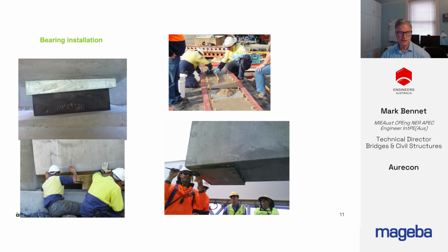There's been a range of different bearing installation details used over the years. A tapered machine plate is an acceptable attachment plate for an elastomeric bearing, but in New South Wales the common practice is to use a pre-moulded epoxy mortar pad bonded to a steel plate as the top attachment plate. This arrangement allows the taper dimensions to be varied to just a few weeks before girder erection if the measured hogs don't match the predicted hogs.